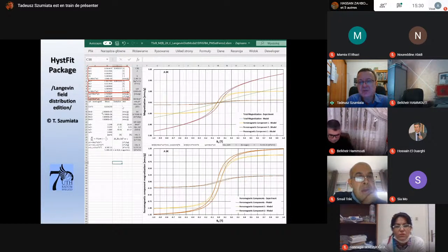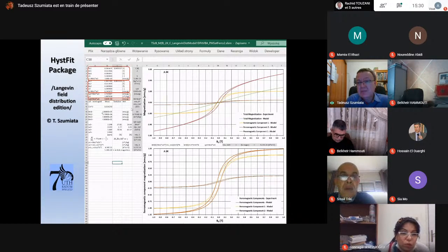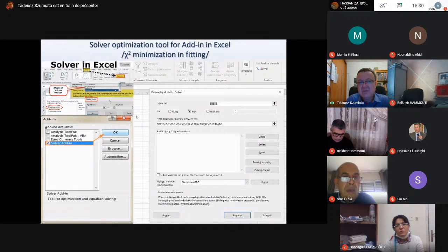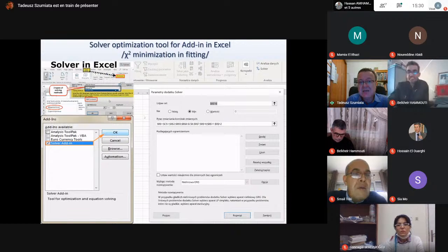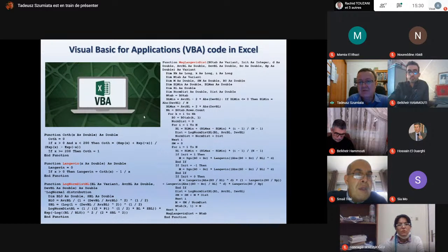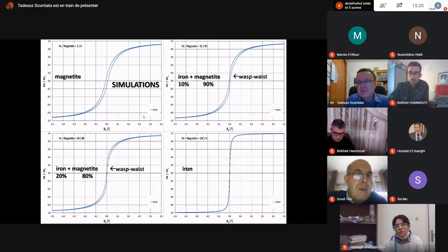And we also prepared special software. I named it HystFit, because many people just plot a hysteresis loop and sometimes determine the coercivity, for example. But in many cases, such a hysteresis loop could be a superposition of several hystereses. That's why we made it for such decomposition. This software is based on Excel and the Solver add-in, which is present inside Excel, and also we had to write some code in Visual Basic, but a very simple one. And this software is good not only for fitting, but also for theoretical simulations of hysteresis loops for mixtures of different constituents.